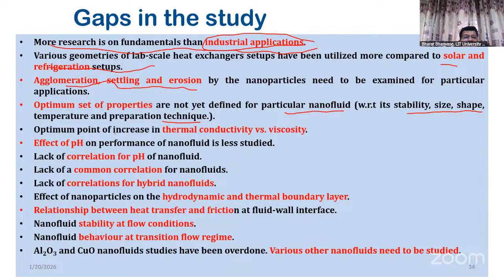Then the optimum point of increase in thermal conductivity versus viscosity, because addition of nanoparticle will increase the viscosity, and that is harmful. With addition of nanoparticle, thermal conductivity improvement is necessary, but at the same time viscosity should be in control. So you have to see what amount of nanoparticle should be added in the system.